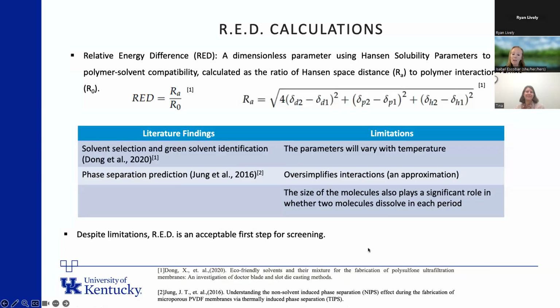Okay, so we start with doing the relative energy difference calculations. We use Hansen solubility parameters to first screen. This is our number one. We take the polymer that we want, and we just look at a variety of different green solvents. Is it even worth going down the path of looking at this solvent, or is it a waste of time because there's no way it would ever dissolve? They're not compatible. And in the RED calculations, what we have in the Hansen solubility is a combination of dispersive forces, polar forces, and hydrogen bonding, and how those interact between the polymer and the solvent. I have a little schematic on the next slide, but I want to start with some limitations of this.